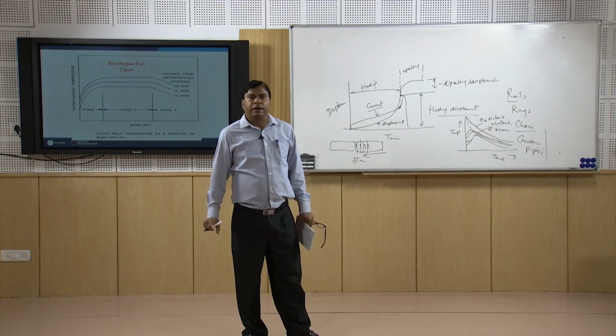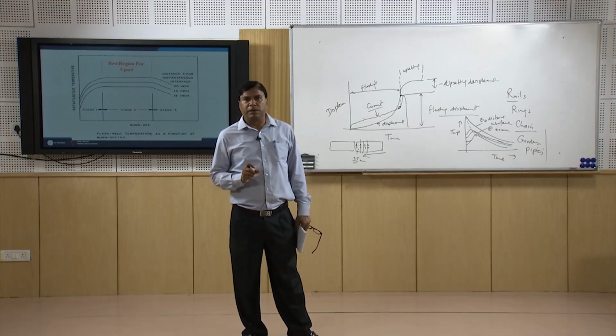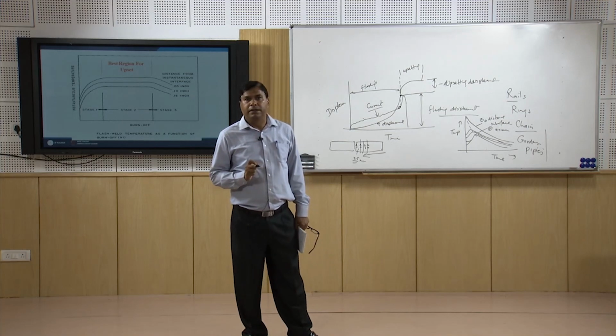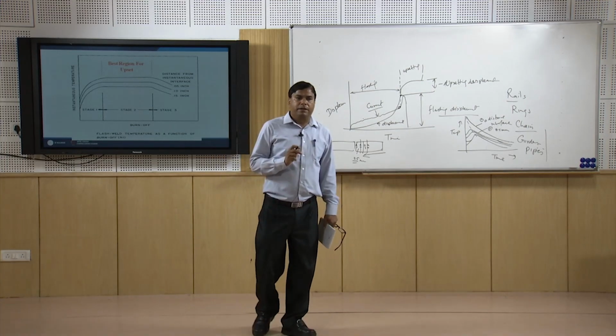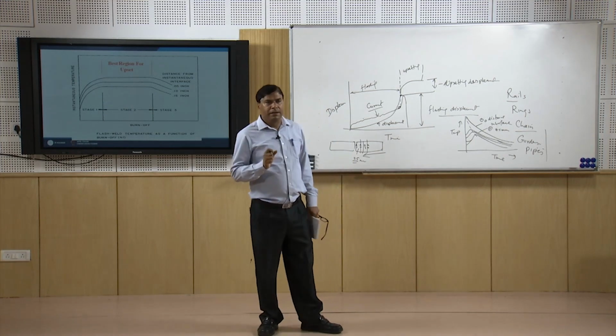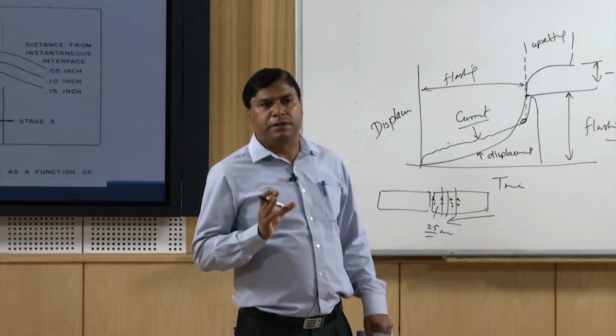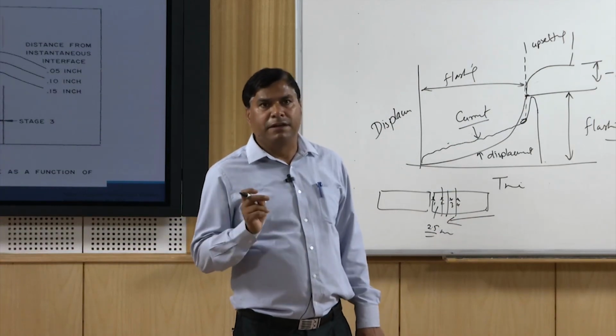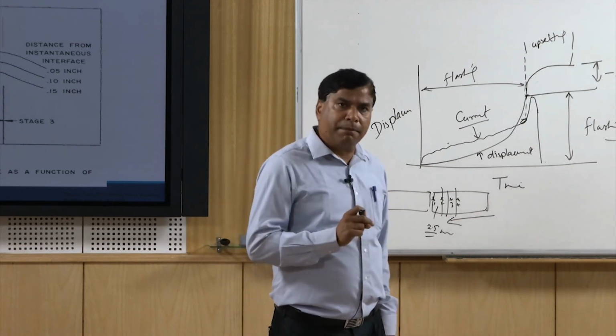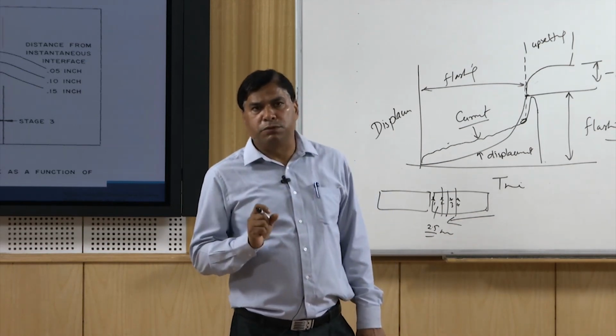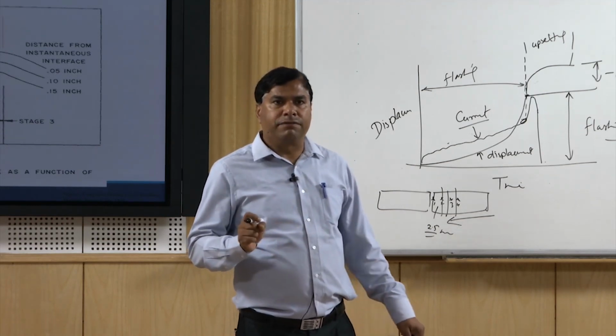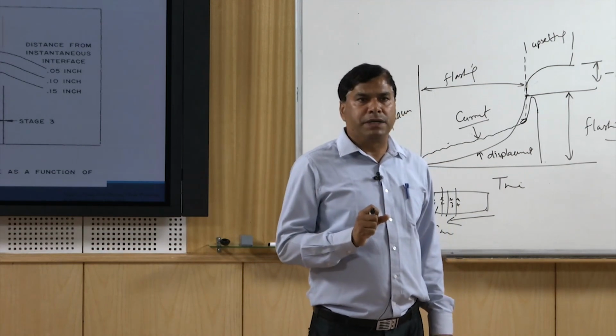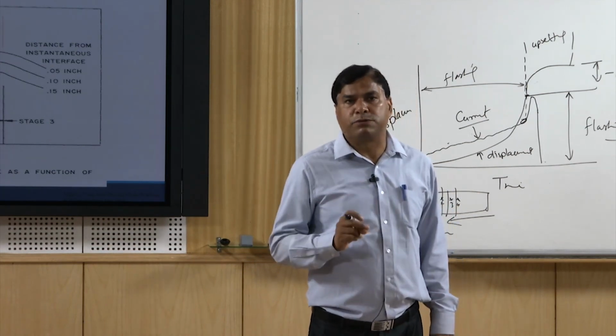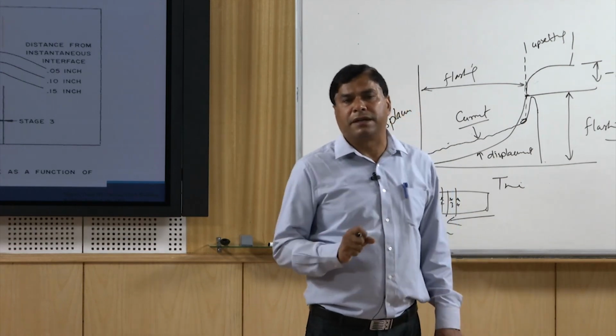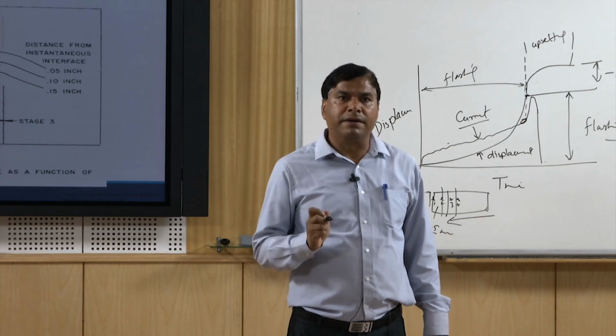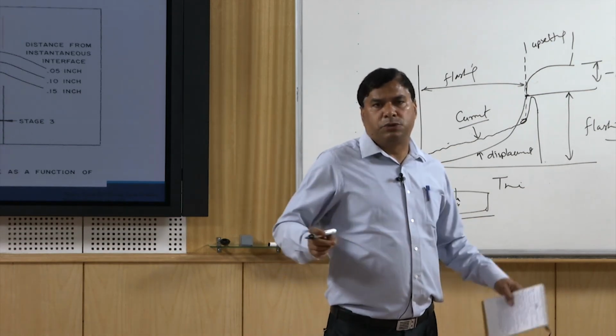In this presentation, we have talked about one of the resistance welding processes, that is flash butt welding. This process is mainly used for the joining of symmetrical section components, and it works on the principle of electrical resistance heating plus flashing or arcing for increasing the temperature of the ends of the workpieces to be joined to the forging temperature, and thereafter upsetting results in the development of the joint. The typical temperature for a steel is 1250 degrees centigrade, and upsetting is done using say 90 or 100 MPa pressure, so that the joint is formed.